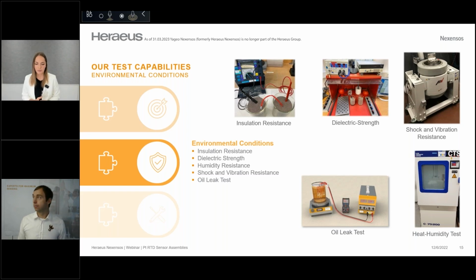Okay, so here you can see that we also stress our sensor assemblies to very specific customer requirements. For example, the customer needs the sensor to withstand high voltages or high currents. And then we can do an insulation resistance test and a dielectric strength test. You will also find on our data sheets an indication about the shock and vibration resistance. The test setup is shown on the top right. It kind of looks like a robot from Star Wars. And then we also carried out an oil leak test. So we exposed, in that example, the EC3032 that we already talked about to heated oil and energized it. And there was no effect on the sensor's performance.